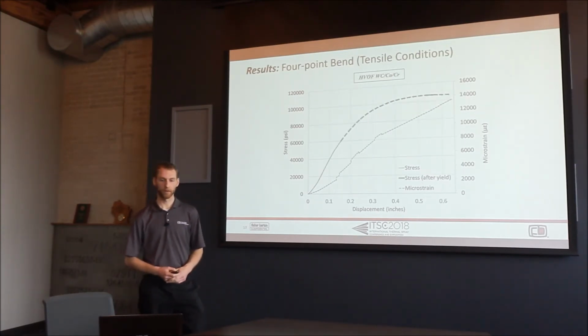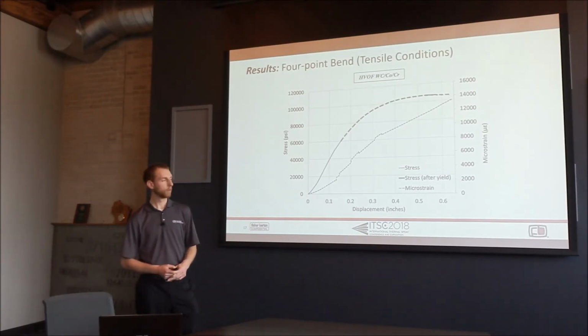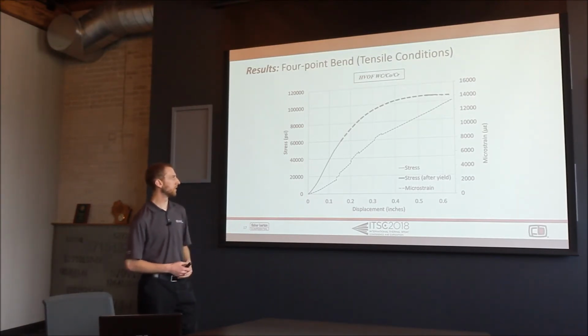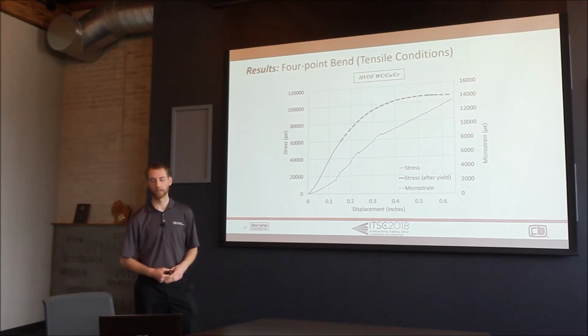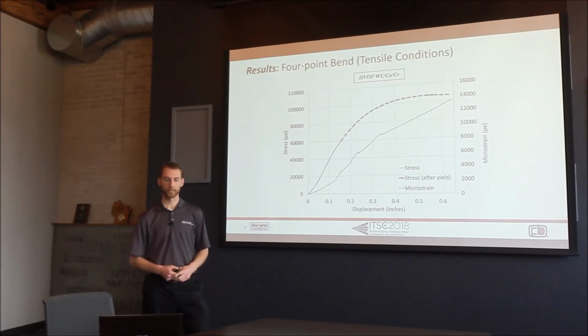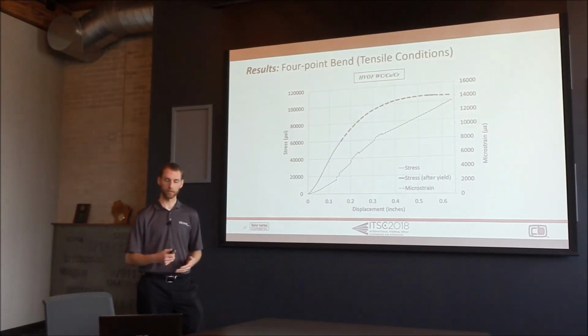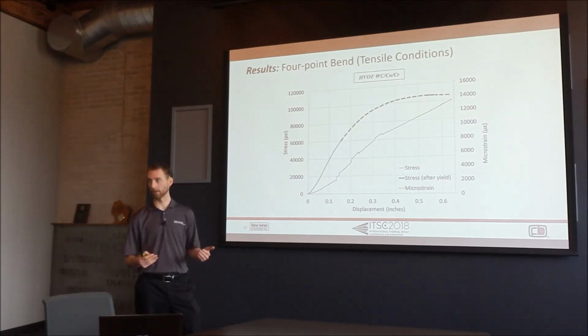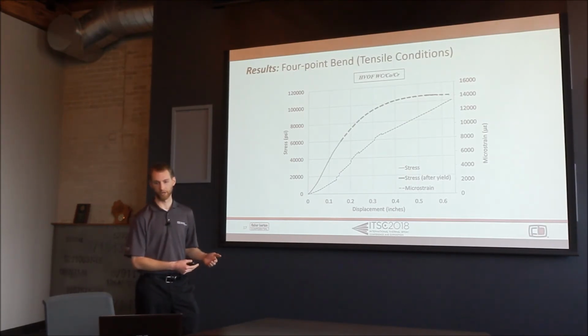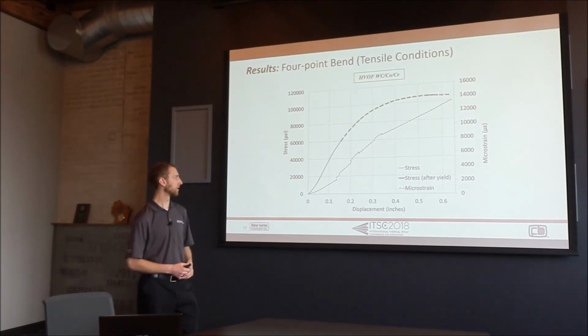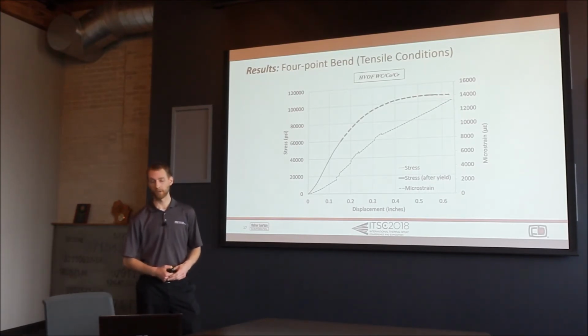A little bit more interesting data here in the HVOF tungsten carbide cobalt chrome. It's not linear, and we also see these jumps and dips in the strain. What that signifies to us is that there are coating cracks, and it's a confirmation of coating cracks as we could audibly hear them during the test. A drastic increase in the strain is going to be a crack directly under the gauge, and a drastic decrease in strain is going to be a crack just outside of the gauge area, basically stress relief. But again, the coating adhesion is well beyond the yield strength of the substrate, still above the ASTM C633 limits.